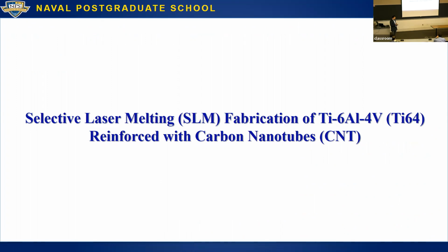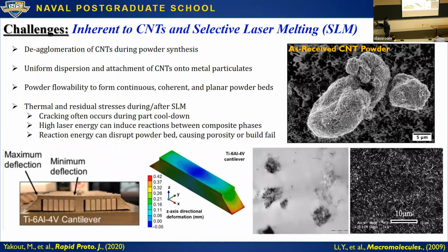We essentially 3D printed Ti-64 composites with CNT reinforcement. And the mechanical property reinforcement part is still very basic, but the processing to get there is quite interesting. So there are inherent challenges to both working with CNTs and selective laser melting. CNTs, when you buy them in bulk, so we're using industrial quantities, we can get a kilogram of high quality CNTs, at least 95% purity, which is definitely important, I'll mention it later, for about $1,000 a kilogram.